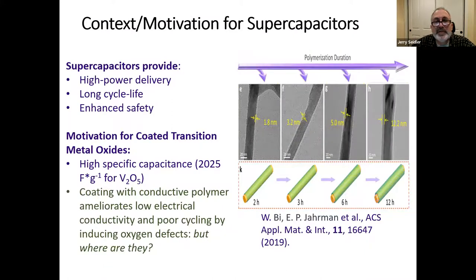We've also studied supercapacitor materials, these V2O5-based supercapacitor materials. And you all likely know supercapacitors provide very high power delivery and long life cycles, so they're interesting for a number of renewable energy applications. And this particular system, the V2O5 coated with a polymer, has very high specific capacitance, which is a very favorable figure of merit. And the coating with the conductive polymer helps deal with the low electrical conductivity of the pure V2O5 by introducing oxygen defects, right? Pure V2O5 is a semiconductor. But the question is, where are the oxygen defects? How do they actually help? And how does that relate to eventual device performance?